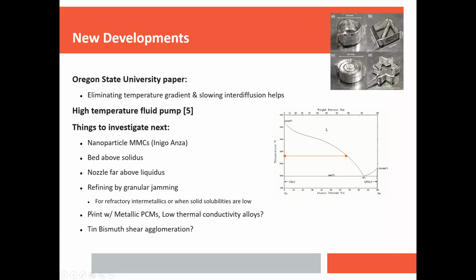And if you can get a semi-solid alloy where the heat of solidification is very large, then you can force it to deliver more heat to the nozzle tip and therefore print more easily. And lower thermal conductivity as well is something to look at. And then the tin bismuth shear agglomeration. And then, of course, the wire production. Continuous casting of small diameter wires from a melt might be very interesting to look at. Anyway, that's everything. And if you have any questions, let me know.